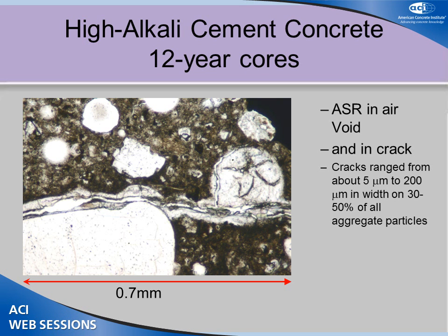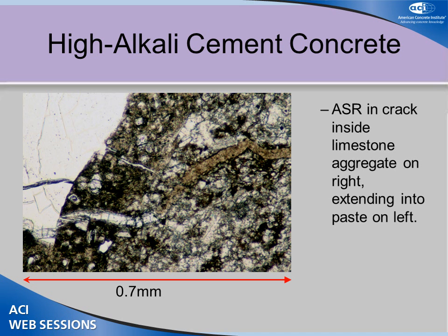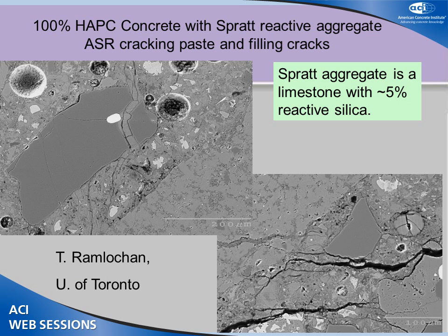And again, here's some gel in the paste of these cores. And again, inside the limestone here, showing the gel in the paste, or extending to the paste on the left. So Terry did some microscopy with backscattered imaging, and this is the high-alkali cement. We can see some of the aggregate particles. The aggregate's split here and it's filled with gel, exuding through the paste. Here's another aggregate particle that's been split and exuding into the paste, and some cracks in the paste here.